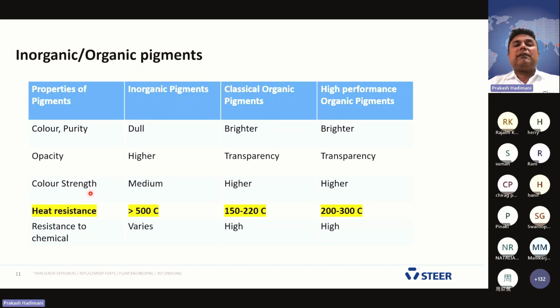Color strength is an important role of the mechanical property. The color strength of inorganic pigment is medium and the color strength of the organic pigment is higher in both cases. Heat resistance, if it talks about each pigment, the inorganic pigments will withstand more than 500 degrees centigrade. But in the case of classical organic pigments, it will withstand 150 to 220 degrees centigrade. And in the case of high performance organic pigments, 200 to 300 degrees centigrade.